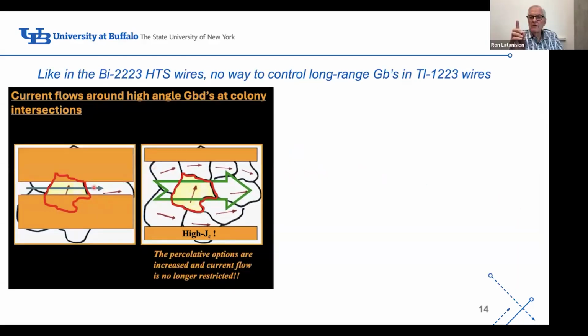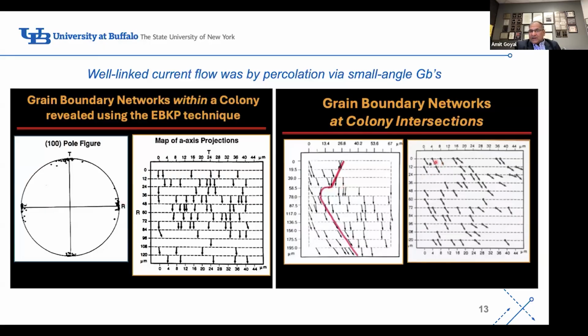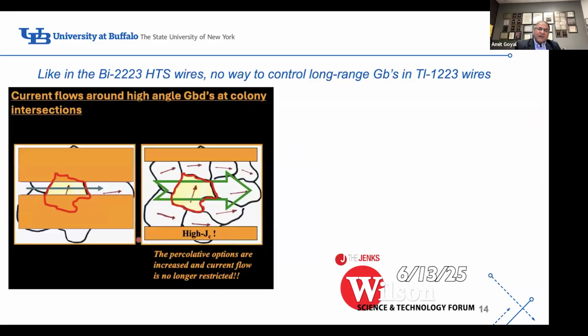So again, in this material, just a question. In order for that to be effective, though, the orientation has to be such that there's direct contact between each one to allow conductivity, right? Yes, there is direct contact. Here we're looking at an individual grain from here to here and from here to here. Now we're going to call a region of locally aligned grains a colony. Each one of these areas is one colony of many grains with common A-axis orientation. So here we've got a high angle colony boundary. If you were to pass current through here, you will not get direct current transmission, but you can get percolative current transmission. That's what I was thinking. Exactly.